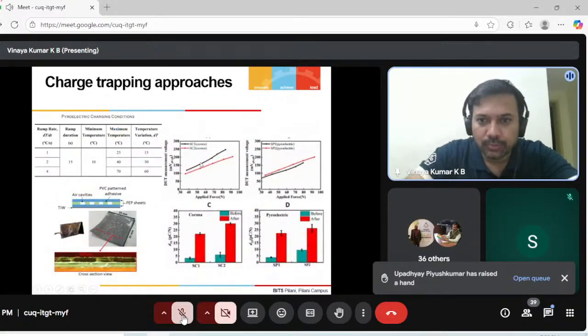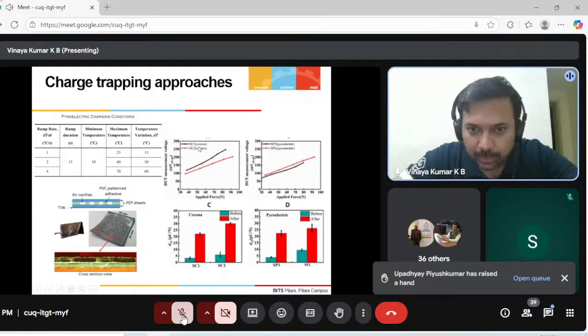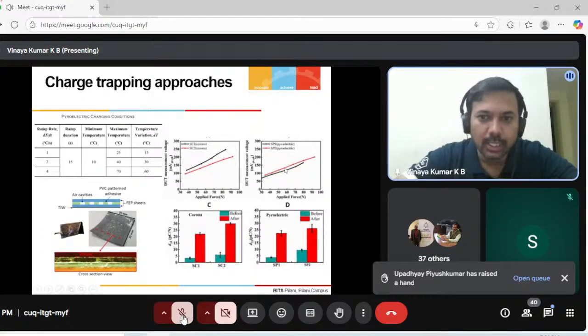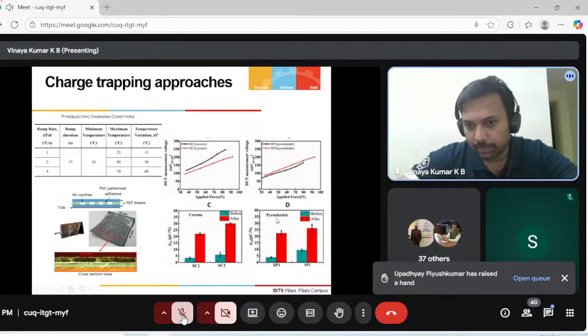Going forward, of course, we compared the corona charging method in similar devices. We also compared our pyroelectric charging method, and both show very repeatable results for several samples, even for several forces we applied. The corona charging, and then after charging and before charging, the pyroelectric charging work we built before and after charging.